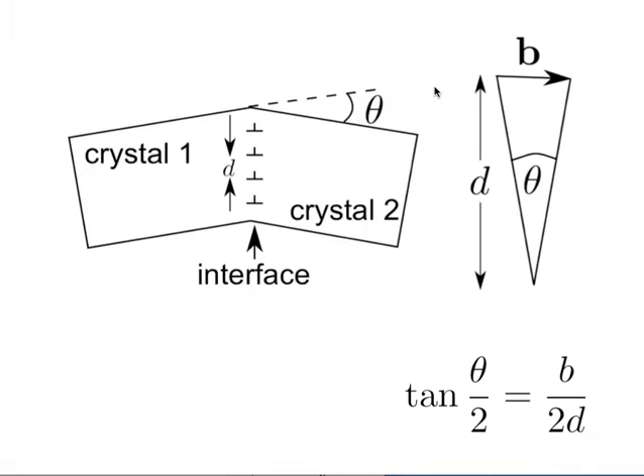If I go back to this image, you've got an extra half plane for every dislocation. So the region here will be in compression because you've shoved in an extra half plane, right? And the region underneath will be in tension. But if I put two edge dislocations on top of each other, then they will kind of compensate, won't they? Because the tension region is next to a compression region.